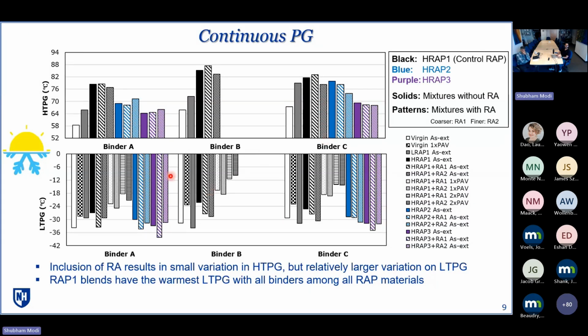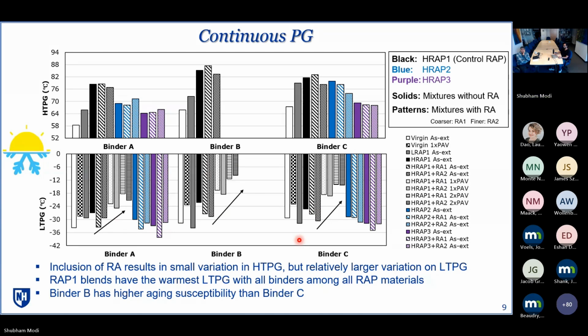Here, as we can see in the HTPG, the inclusion of RA resulted in very small variation compared to the low temperature side changes. The RAP1 blend has the warmest LTPG with all binders among all RAP materials. With the aging, we observed that binder B has higher aging susceptibility than binder C, even though they had similar performance grades.